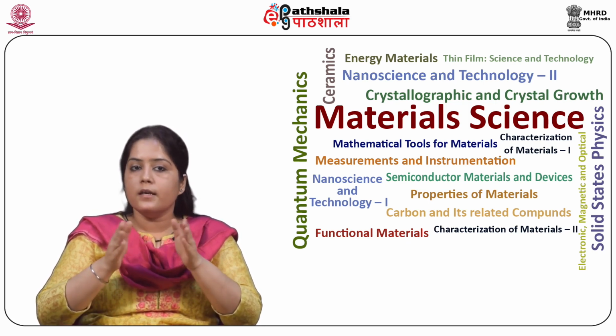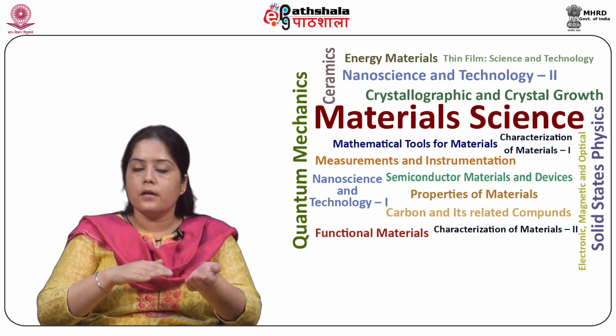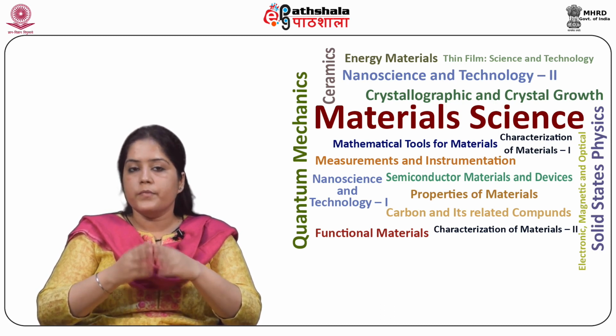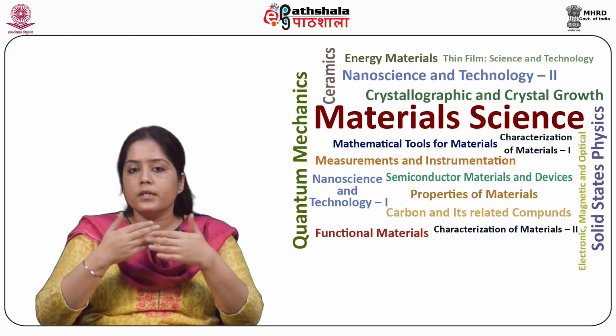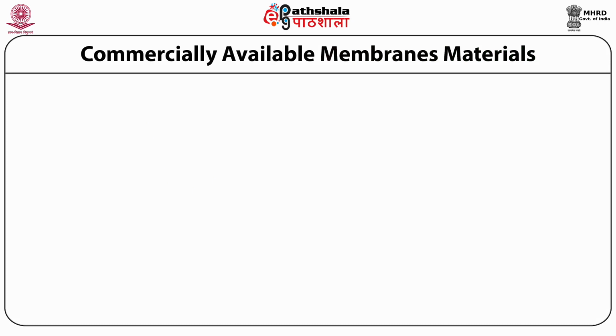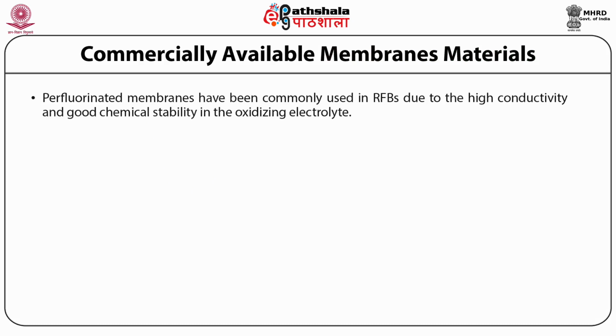However, recent studies suggest that AEM could effectively reduce the crossover of vanadium ions in VRFB due to the Donnan exclusion effect, which is an electrostatic repulsion between the cation groups within the membrane and the electroactive species. Commercially available membrane materials: perfluorinated membranes have been commonly used in RFBs due to the high conductivity and good chemical stability in the oxidizing electrolyte.